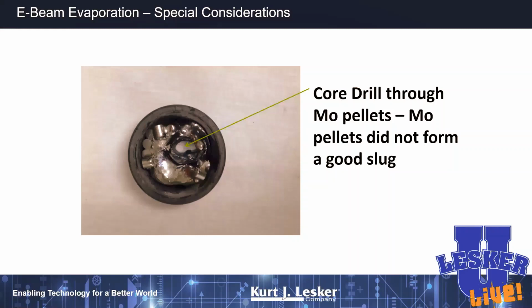Here's an example of somebody who actually core drilled through the material into the gun. So these are molybdenum pellets here. He didn't pre-melt them to make one solid slug. You can see the pellets off here because he wasn't sweeping the beam, and it didn't even get molten at all. And so he E-beamed through the material, E-beamed through the crucible, E-beamed through the copper hearth, and hit the water cooling jacket. And when he did that, the E-beam system filled up like a washing machine. That's considered bad. Don't do that. That will really mess with your day.